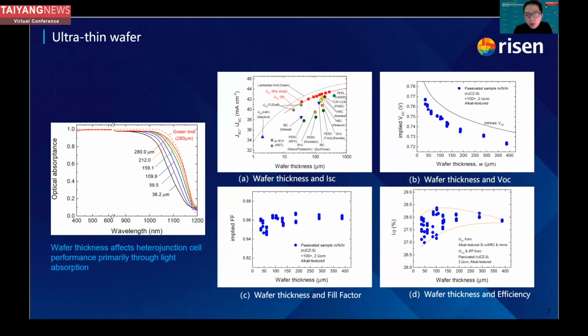On the fourth diagram on the left, the first one shows the relationship between ISC and wafer thickness with the thinning of the wafer. We're seeing that the ISC slightly decreased, but in contrast, with the thinning of the wafer, the VOC increased a little bit. To bring these two factors together, we look at the two pictures in the bottom left, showing the relationship between fill factor and wafer thickness, and between efficiency and wafer thickness.